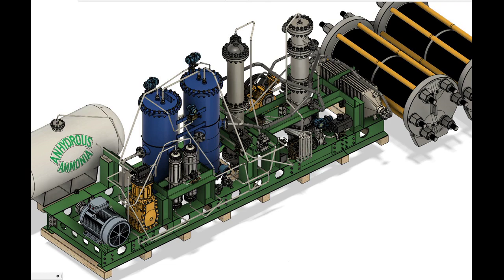To minimize thermal losses, Pachari Technologies has designed a novel insulation system utilizing microporous insulation that encapsulates the high-temperature ammonia reactor module. The entire converter and exchanger assembly is wrapped with many centimeters of rounded insulation board, and sealed with high-temperature sealant. Microporous insulation is made from silica and aluminum oxide powder or fibers, whose interconnecting pore size is kept below the mean free path size of air molecules.